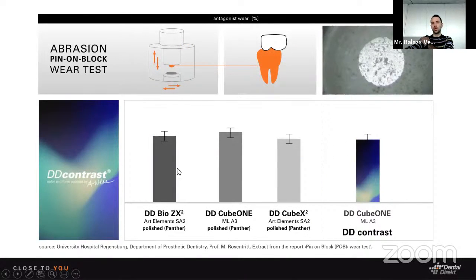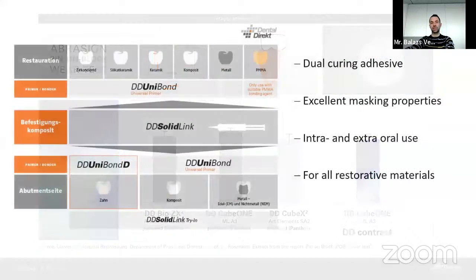After that, we also took 3 examples from our materials. We polished them, all of the crowns from different kinds of materials, and we analyzed how they react. Just the glazed crown, glazed with contrast material, and we saw that with our glaze, thanks to that micro ceramic structure, we reached the same level with our contrast material as we have in a polished crown. And of course, it was done again by the University of Regensburg, and they did it also as an abrasion test. So we are sure that when we use our contrast glaze material on our zirconia material, we will reach a really good solution for the antagonist teeth.